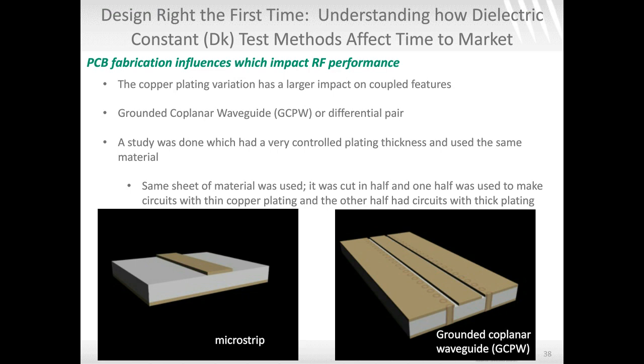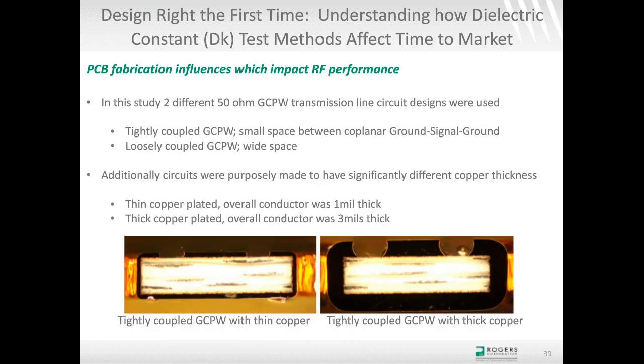And I looked at microstrip and then several different versions of grounded coplanar waveguide. Long story short, microstrip had very little influence. The RF performance of the microstrip had very little influence due to the difference in copper plating thickness. However, the grounded coplanar waveguides did show a pretty remarkable difference, especially at millimeter wave frequencies.